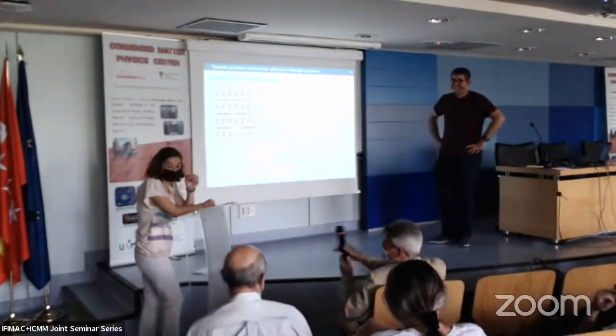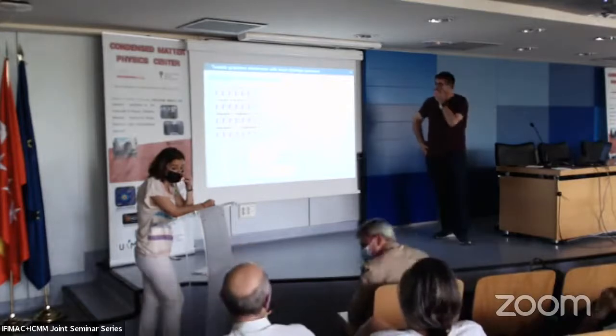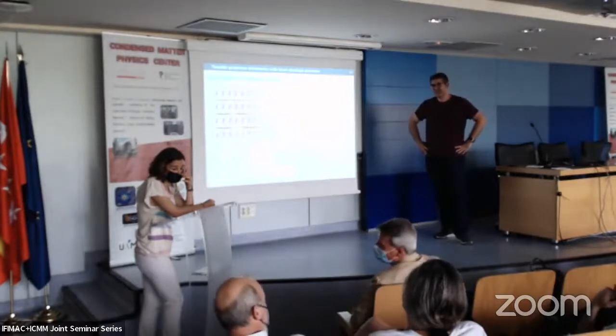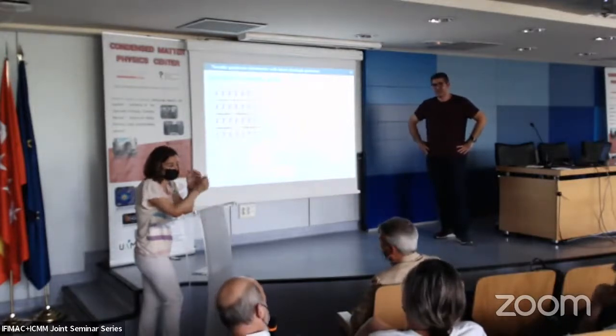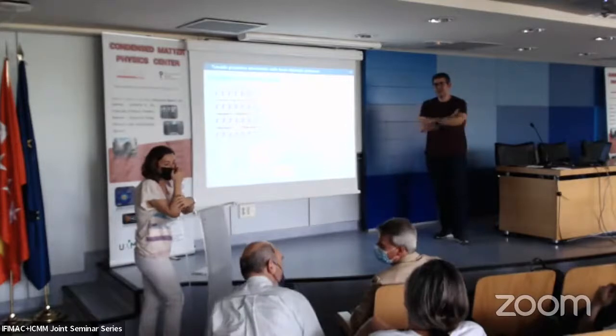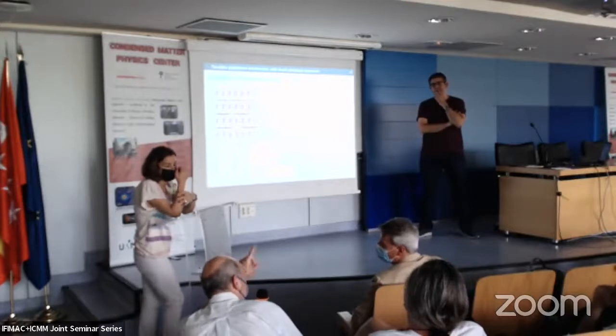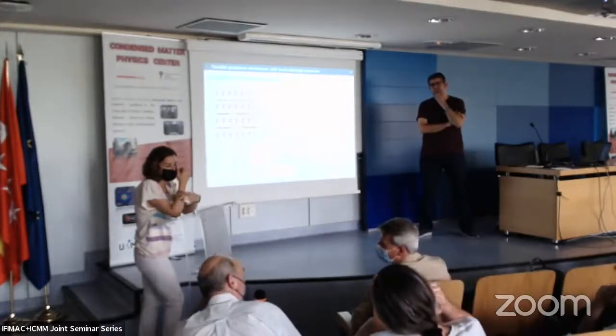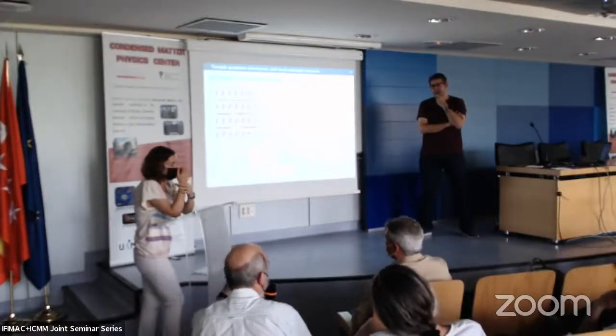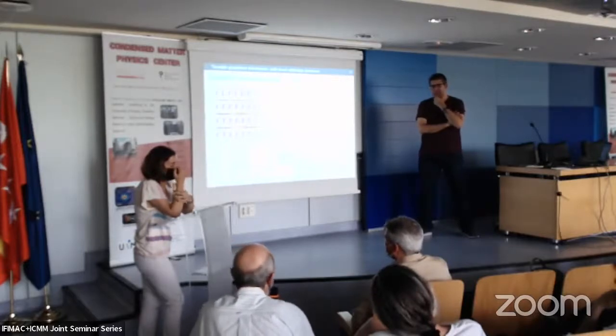In truth, I can't remember. I barely remember. Yes, but it's carbon oxygen. But the important point here is that there are very few bonds that are necessary to keep the graphene so close to the silicon. And it was a very important and puzzling thing in the experiment, because if you have seen the spectra, the contribution in the XPS spectrum was very, very small. So it was our surprise. And we tried many different configurations, which I remember very well. And only just a few carbon-oxygen bonds were able to keep the graphene much closer.